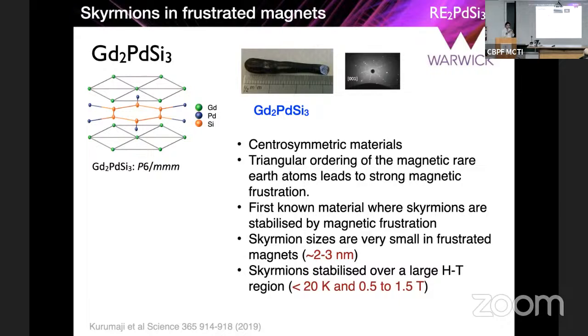So wherever there is a triangular lattice of the rare earths, invariably there's magnetic frustration in this. And sure enough, there is magnetic frustration, very strong magnetic frustration here. And this was proposed as one of the first materials where skyrmions are stabilized by magnetic frustration. Okay. Now the skyrmions in these materials